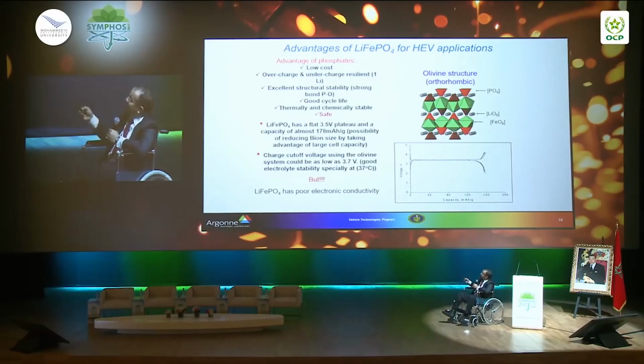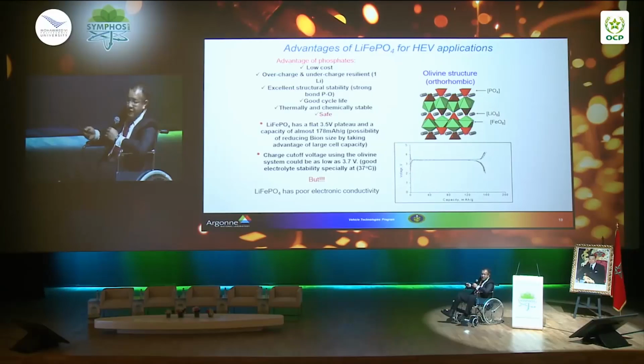So these are all very attractive characteristics, but the problem is it has very poor electronic conductivity. This is a serious issue, because if you really want to move lithium through the particle, it will be very difficult, and therefore you cannot achieve good performance. One way to address this is to use nanomaterials, so you reduce the pathway of diffusion within that particle. But when you do that, you create an issue of density. The packing density of the material becomes very low, and therefore the energy drops. So what I would like to show you today is an idea to fix this problem.